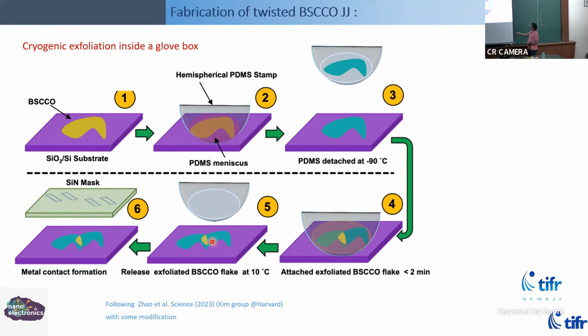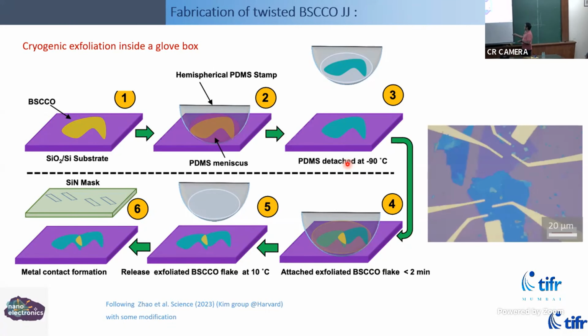We figured out a way to take a crystal. If we want two arbitrary crystals twisted by an angle, then we need to start from one mother crystal, peel off two copies, and then put them back together. That's the strategy we use. So we start with a mother crystal. We peel it at very low temperatures, peel off a few layers of it, and assemble it to realize the overlap area, which is the Josephson junction. So it looks like this. These two pieces have come from the same crystal, but they were peeled at very low temperatures, which ensures that the oxygen doesn't leak out. And then within a matter of a minute, you put them back so that the interface is again buried.